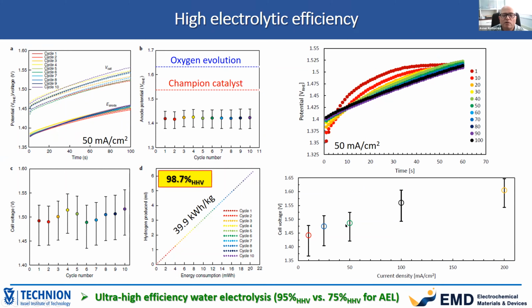And we can also increase the current density up to 200 milliamps per centimeter square. These results were made at a relatively low current density of 50 milliamps per centimeter square, but today we get the same result with higher current density approaching 200 milliamps per centimeter square, which is already at the level of alkaline electrolyzers.